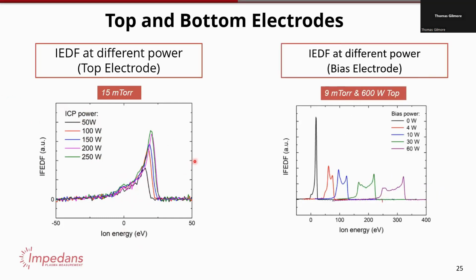Then if you apply different powers at the bottom, in this case, when there's 0 watts at the bottom and power applied at the top, you get this peak at the plasma potential, and you have a little tail due to collisions. As you increase the bias power, you get higher and higher energies. But you can see here, it's not so linear. The power goes 0 to 4 to 10, 30 to 60. It's not linear. Similarly, the peak splitting changes as a function of power. So that's another problem.